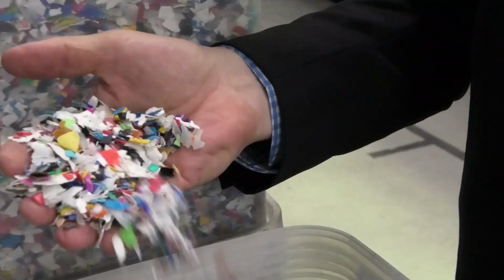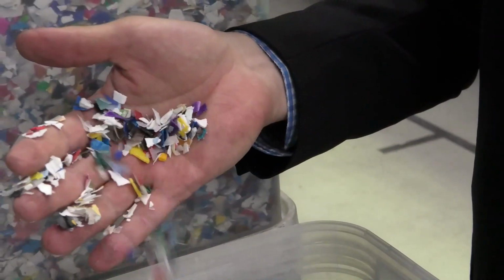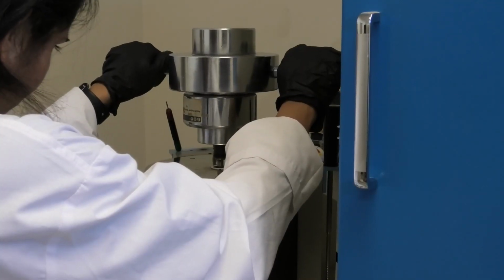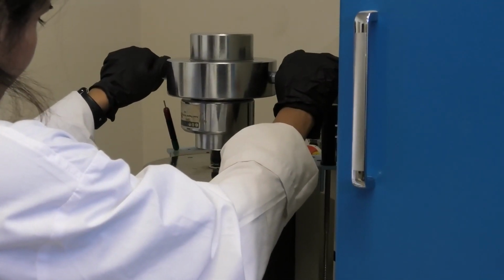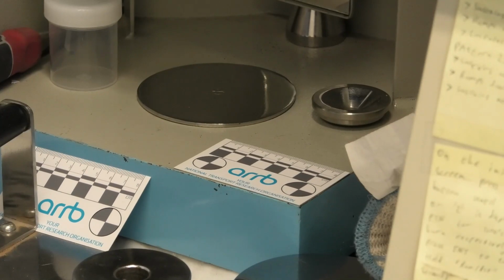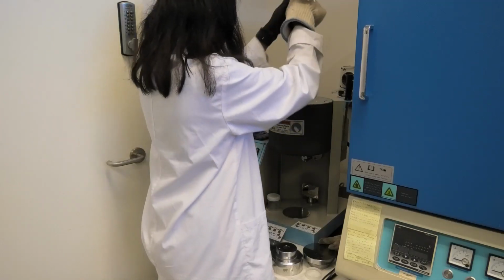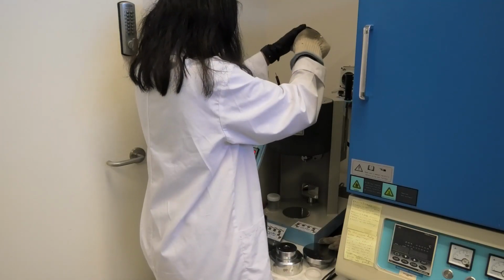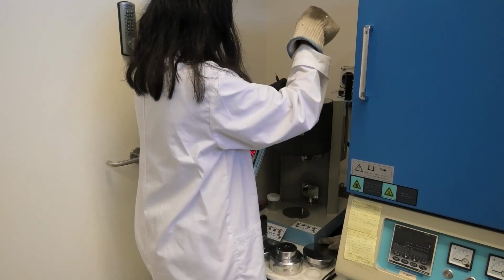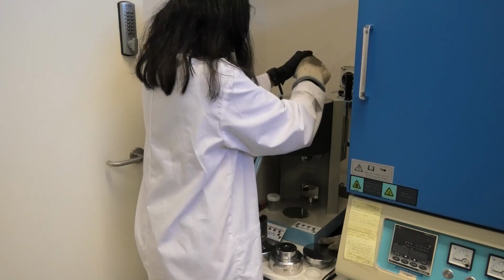Well, it's called the Melt Flow Index test, and it's abbreviated as MFI. And basically it determines the amount of molten plastic that flows through an orifice under load at a given temperature. In this case, for polyethylene, we're melting the material at 190 degrees and we're applying a load, and that load pushes the molten material through a very small hole.